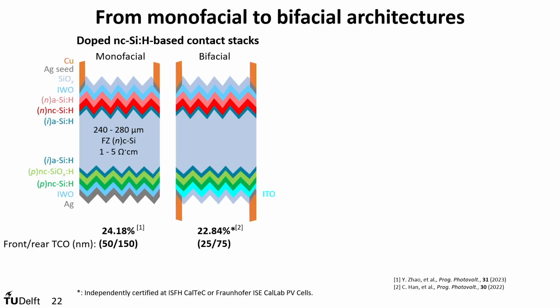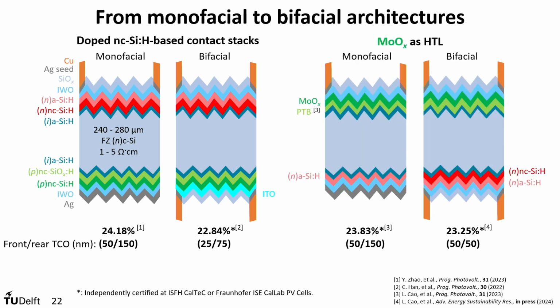Then we went on to deposit different types of solar cells, from a monofacial to a bifacial stack, in order to see how much we can push down the thickness of the TCO with respect to the utilization of copper plating. And you see that we can have relatively good devices with nanocrystalline silicon-based doped layers, but also when using transition metal oxides as a specific case for hole transport layers. Especially in the case of moly oxide, we have world record certified efficiencies for both mono and bifacial representations.